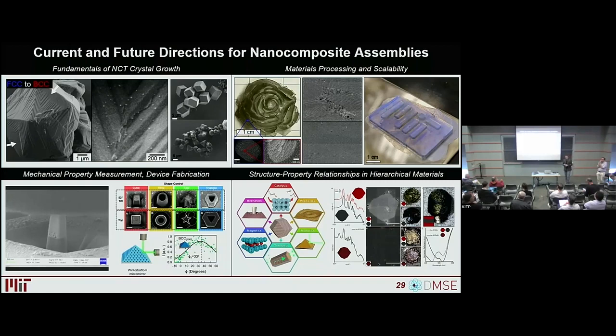In terms of the polymer length, again, we typically work between about 4 and 25 kilodaltons, so that's roughly 5 to 25 nanometer thick shells. Larger than that, the assembly conditions tend to be too weak to actually drive the formation. Smaller than that, it could work, but making polymers smaller than 4K is next to impossible. You can make them, but purifying them is a pain. So.